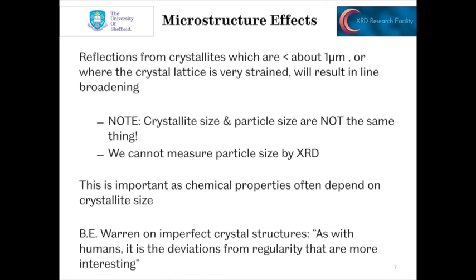Microstructure effects tend to be much more of an issue. If you've got reflections from crystallites that are less than about a micron, maybe a tenth of a micron, or where the crystal lattice is very strained, then you'll get broadening of the XRD lines. It's important to note when we talk about crystallite size from X-ray diffraction data, it's not the same as particle size. We cannot measure particle size by XRD. What we measure is the crystallite size, or even more properly, probably the coherent scattering domain size.